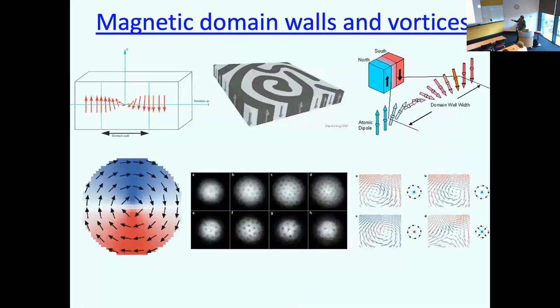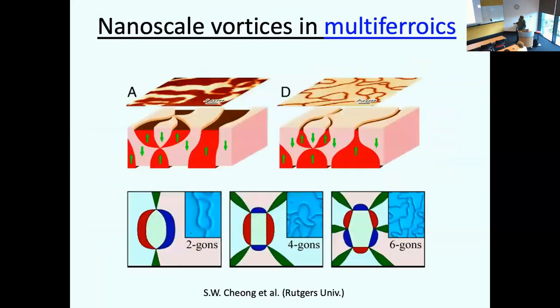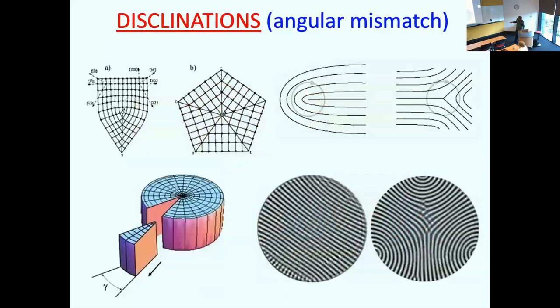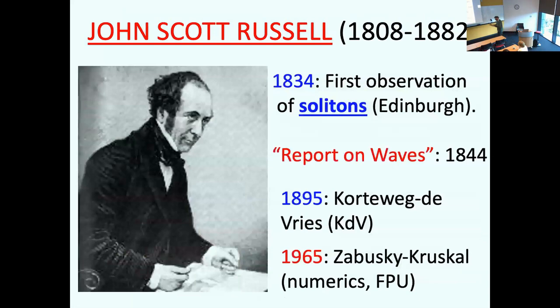And of course, in magnetism, you have domain walls, vortices. It's very important for the magnetic storage memory you have in your computers. Similarly, you have materials in which polarization and magnetization couple. It's called magnetoelectrics, or more generally multiferroics, and you can get very interesting kinds of experiments. Vortices and topological defects. And finally, here you have some kind of disclination. Basically, you cut out something, join it, you get a disclination. I will say a few words about solitons, and then I'll come to skyrmions.